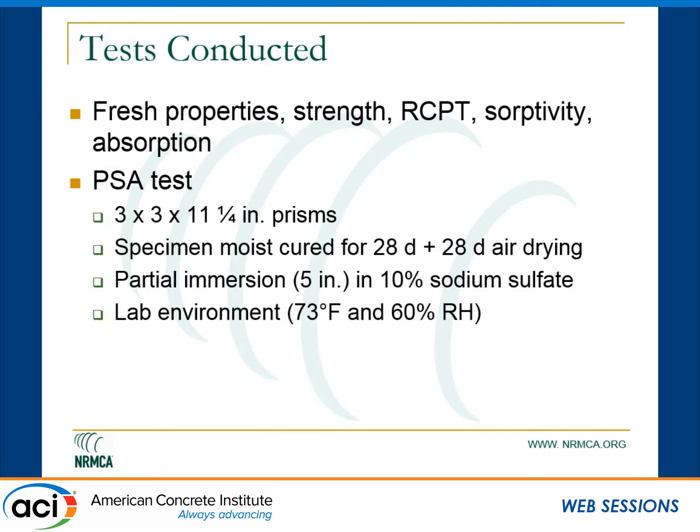We took 3×3×11¼-inch prisms — the typical shrinkage prisms. We moist cured them for 28 days and then 28 days air cured. Then we partially immersed them to a depth of 5 inches in a 10% sodium sulfate solution. The top part was exposed and the bottom part was immersed. The lab environment was about 73°F and 60% humidity. We let that testing go on for about 12 months, but there was really very little failure happening, so we wanted to do something quicker.